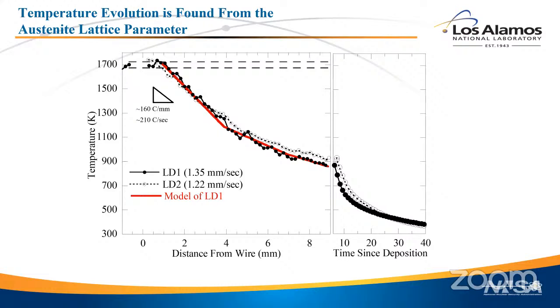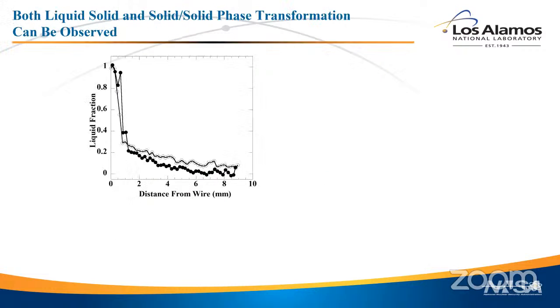So now we can pull out the temperature as a function of time. We can pull out the liquid solid fraction. So it starts out as purely liquid. It drops pretty quickly. And again, we're not quite fast enough to measure liquid to solid. Liquid to solid happens really fast. We get 1 or 2 data points in the interim. But then it's sort of slowly, it's mushy zone. We really don't believe there's any liquid out there at 5 millimeters from the wire. That's certainly not true. But anyways,